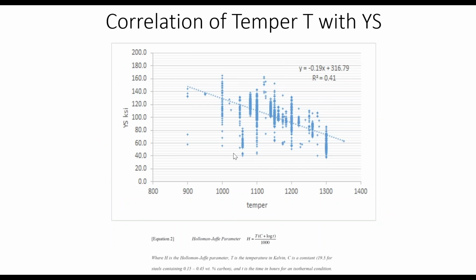We know that tempering temperature makes a difference, and so we really want to include tempering temperature in the calculation if we're going to try and predict properties from chemistry. We might even want to look at different tempering temperatures so we can select the one we want. And so even though I only get a 41% correlation because the chemistry makes a big difference, I do show that there's a real effect of tempering temperature.